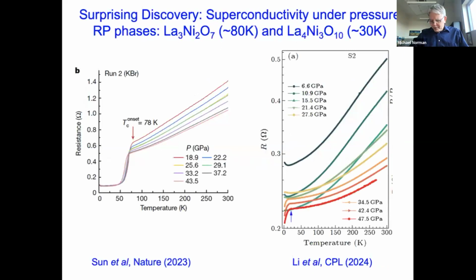So now let me turn towards the end to the recent discoveries, where we're going to have a lot of talks at this meeting. Based on the previous results on 214 nickelate, I don't think anyone really thought that we would see superconductivity in these Ruddlesden-Popper phases. At ambient pressure, both of these materials, the 327, which is the N = 2 Ruddlesden-Popper, and 4310, which is the N = 3 Ruddlesden-Popper phase, have very pronounced density wave transitions near about 140 Kelvin. And they were substantial transitions, and so no one really thought that this would be a great place to look